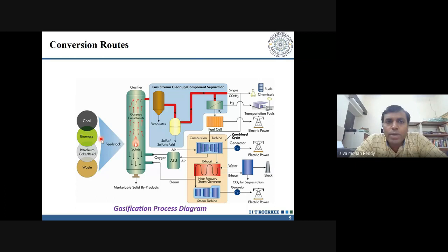The other conversion route that is popularly known is the gasification technology. This gasification technology is a well-known technology which has been known to the research community over the decades. Any carbon source, that might be coal, biomass, petroleum coke, residue, or any waste, can be fed to a gasifier. The gasifier is maintained at very high temperatures, typically more than 1000 degrees centigrade. Some gasifiers might go as high as 1800 and 2000 degrees centigrade also.